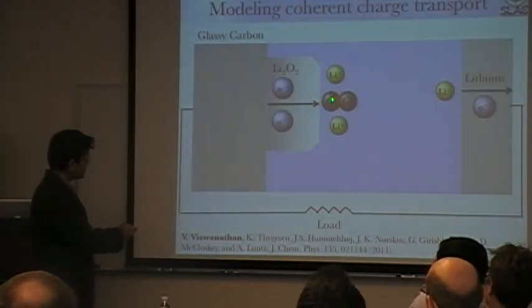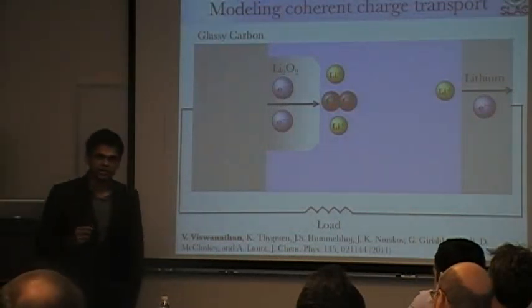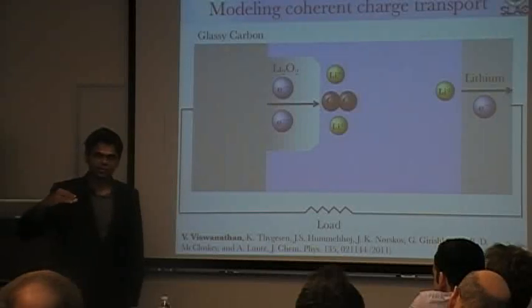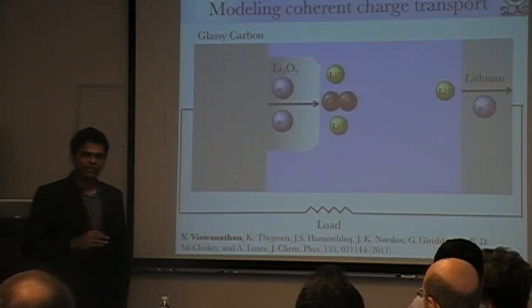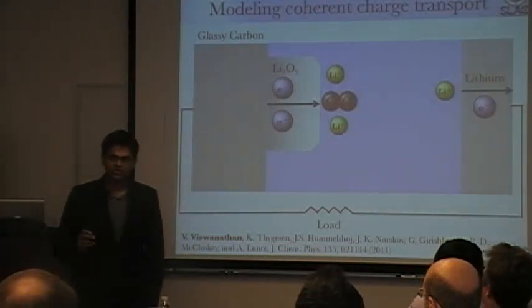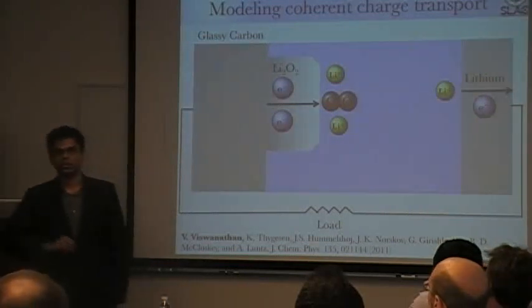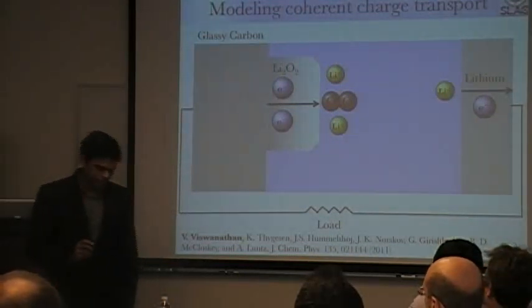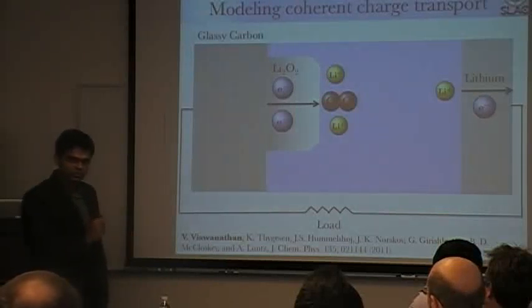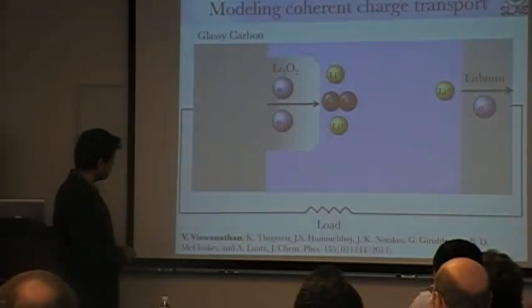Two lithium plus and oxygen and electrons react at a certain chemical potential. Right? So there is a well-defined chemical potential relative to vacuum where this reaction happens. And so if we can match a material that has a work function which lines up with the chemical potential of this reaction, then you can substitute that also by a metal. It turns out that gold has a work function that is in the range of discharge of this battery. So we probe the conductivity of this system in a metal insulator metal configuration.